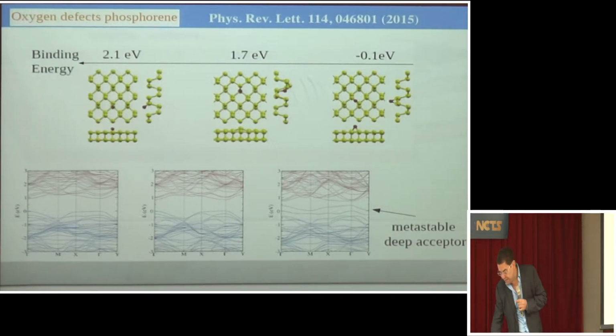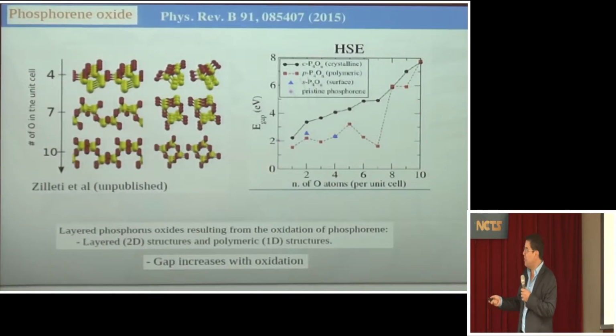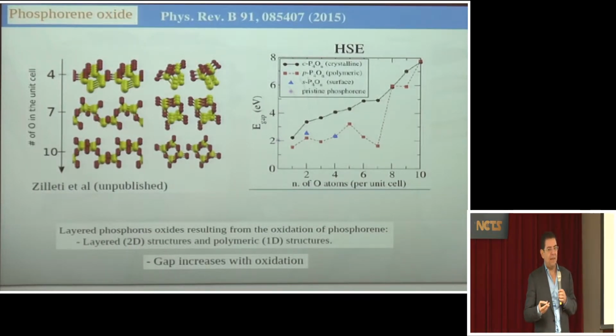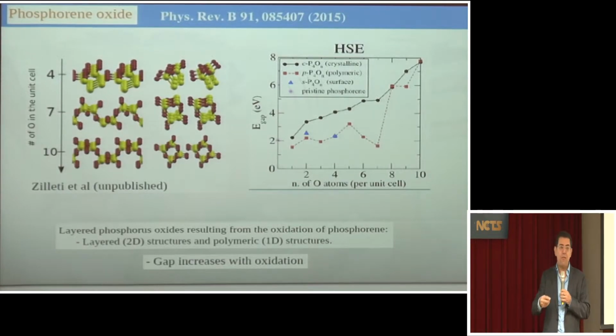Okay? But that's exactly very similar. But the interesting thing is that this is a numerical study of the possible oxidized forms of phosphorus. It turns out that you can have crystal oxides of phosphorus. And in that case, these crystal structures are periodic, they are crystalline, and they have different forms. They can be like tubes, or they can have this structure here. And the interesting thing is that, and this has not been done experimentally, this is very challenging.